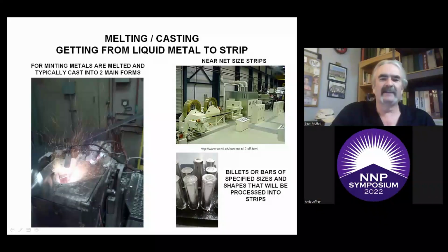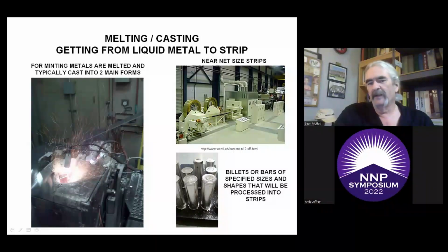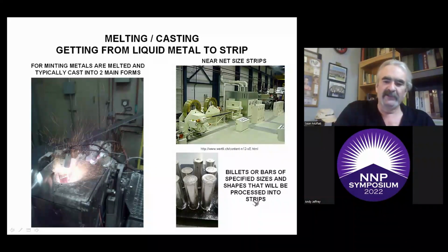Now, melting and casting: you have to get from liquid metal into strip. So for minting, metals are melted and typically cast into two main forms. As you see, we've got melting down in here, getting them ready to be poured, and you go through these machines over here, and you can have it continuously cast into a strip, or if you cut them off in sections, they'll just be bars. The strips are coiled up just for safekeeping and easy processing. Or you can pour them into billets or bars. Right here we have billets shown that will be processed later into strips.